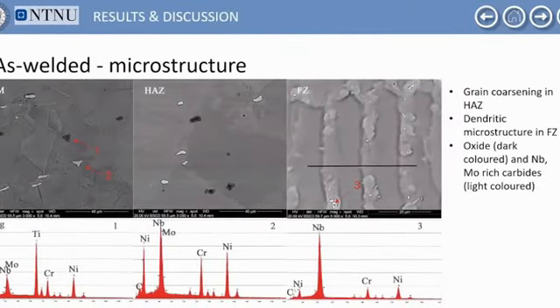These are the results in terms of SEM micrograph of the as welded joints. We observe a grain coarsening in the heat affected zone as expected, and a dendritic microstructure in the fusion zone. We also found different precipitates. The dark colored precipitates were identified as oxide. On the other hand, the light colored precipitates were identified as carbide enriched in niobium and molybdenum.